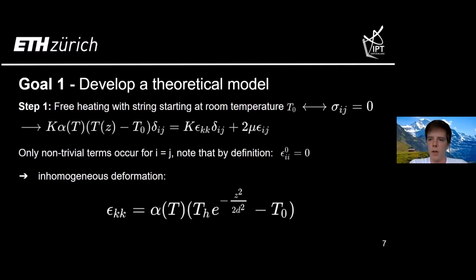Now, I come to the development of the theoretical model. I modeled the process of the free heating as heating without any stress on the bottle. Therefore, the stress tensor is 0. And this leads to the fact that I can get an expression for the deformation tensor here, since the tensor with the subscript 0 has diagonal entries that are 0, and therefore I have a deformation from the heating with the Gaussian function. And now comes the important step of the sudden cooling.